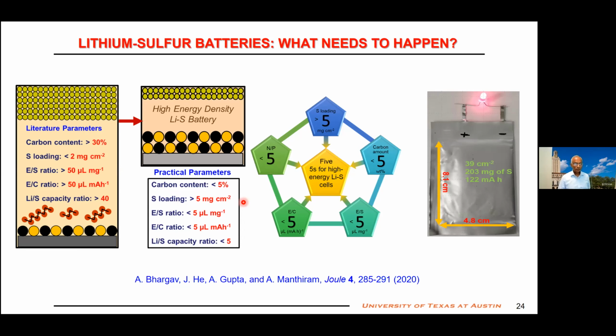Yes. So our goal is to take less than 5% carbon, sulfur loading of at least more than 5 milligram per centimeter squared, take less than 5 microliter per milligram, and have better utilization. So this is what we have been focusing on. And then testing with coin cells is no good. We have to test with pouch cells. We do a lot of testing with pouch cells so that we can have more reliable and better measurements.